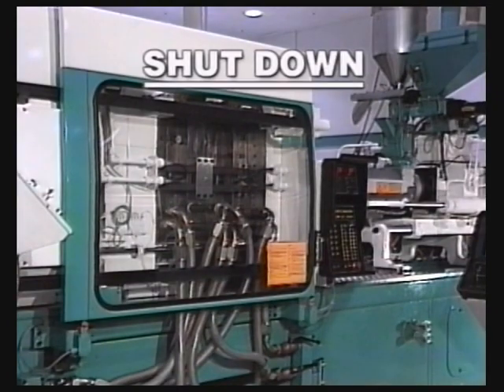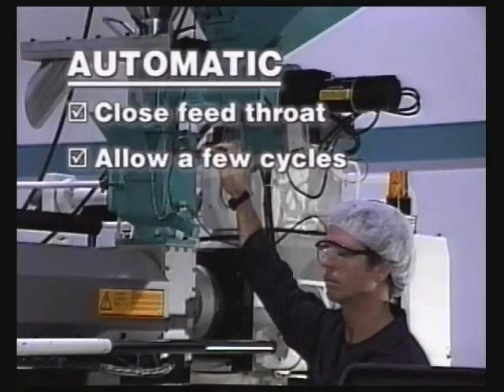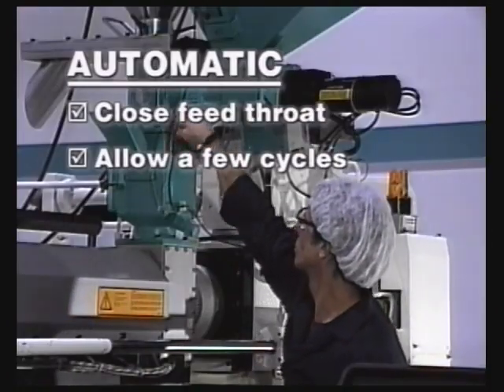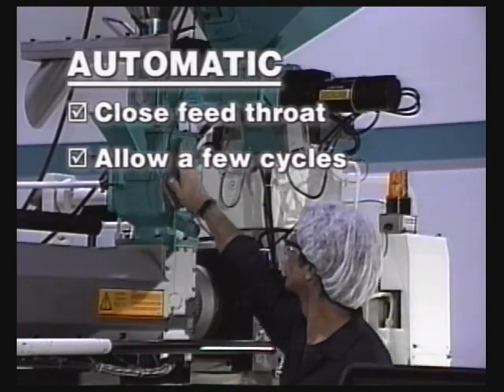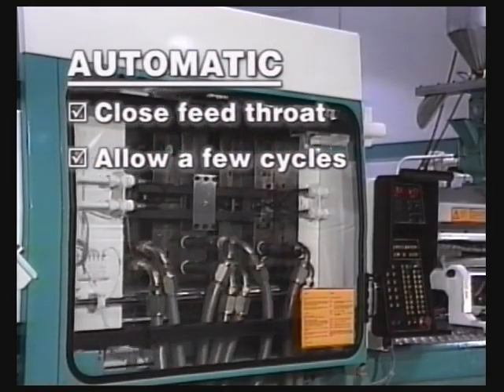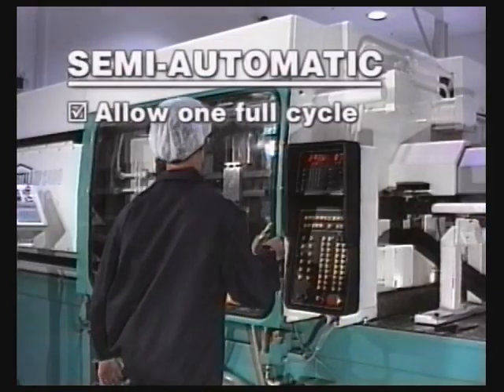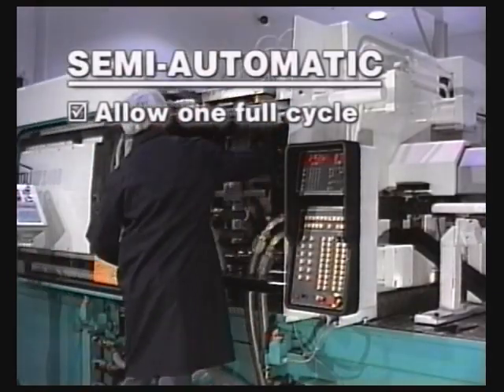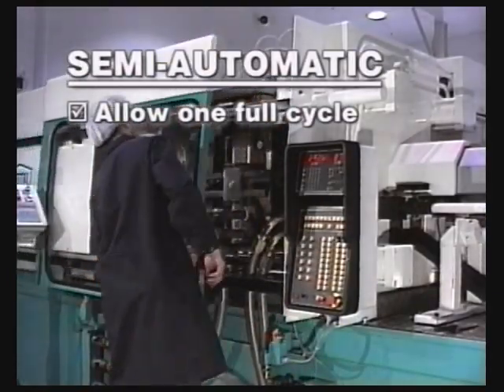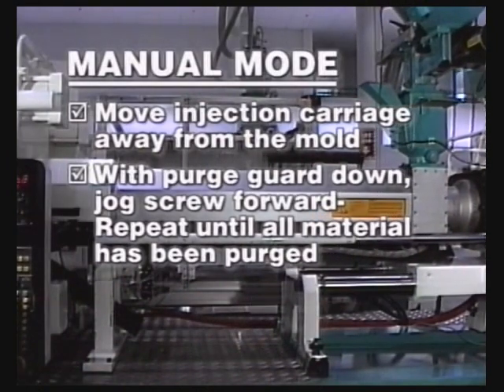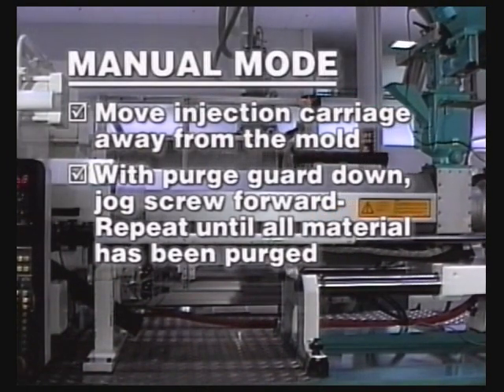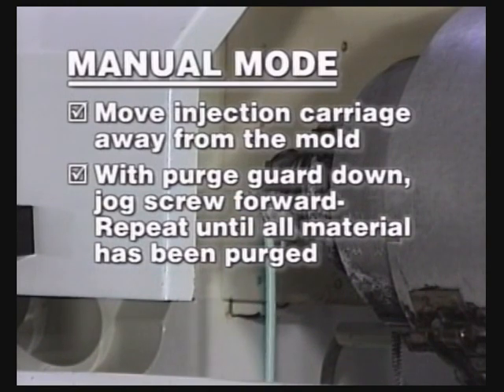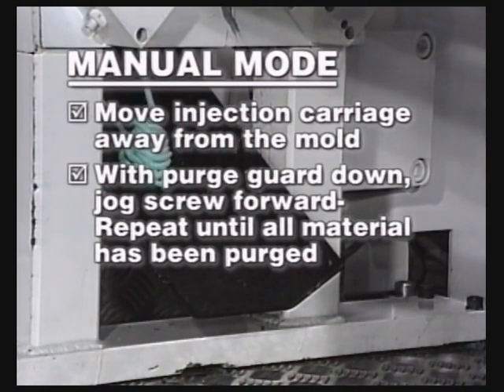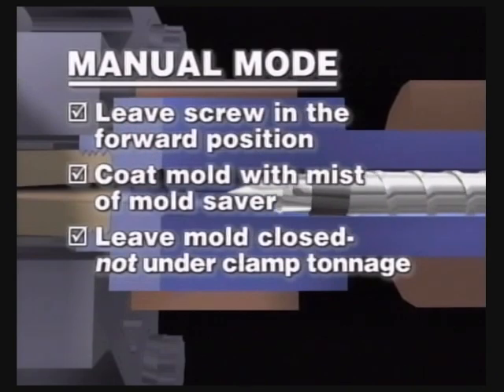When shutting down the process, close the feed throat to prevent any more plastic pellets from entering the screw and barrel assembly. After the machine cycles a few times, put it in semi-automatic mode. After the completion of one cycle, place the machine in the manual mode. Move the injection carriage away from the mold. With the purge guard down, slowly jog the screw forward, repeating this procedure until all of the material has been purged. Leave the screw in the forward position.